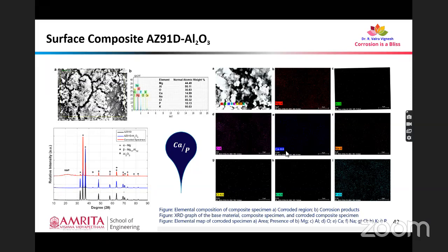Okay, and we have done elemental mapping analysis that also confirms the overlapping of calcium and phosphorus, which confirms there is a possibility for the formation of calcium phosphorus salts, calcium phosphorus based salts. And XRD analysis also confirms the presence of hydroxyapatite based crystals. So the small peak between 20 and 30 degrees corresponds to HAP. So that was confirmed through XRD analysis too. So here is the phenomenon that is taking place in the material.